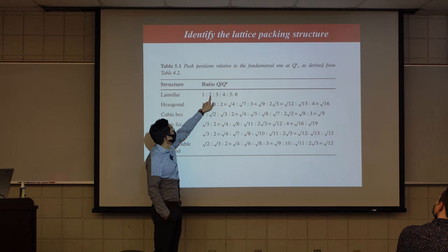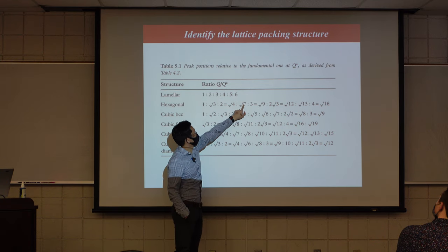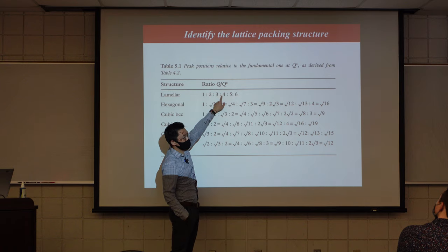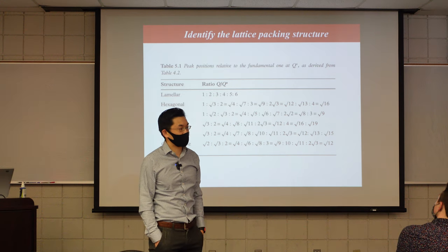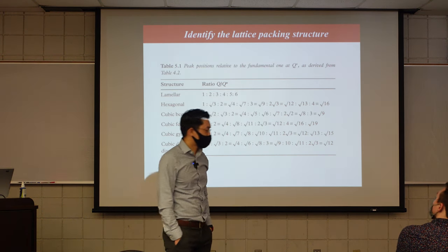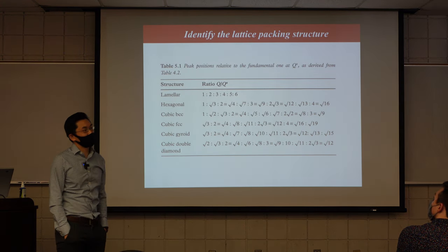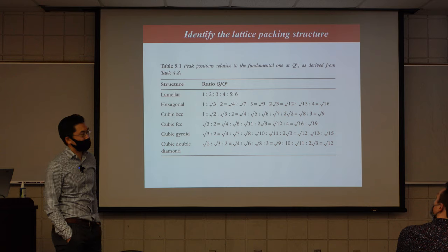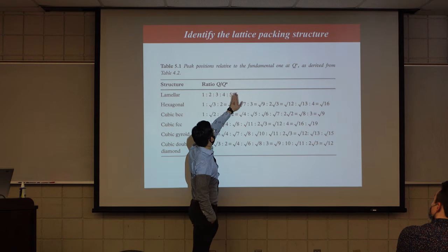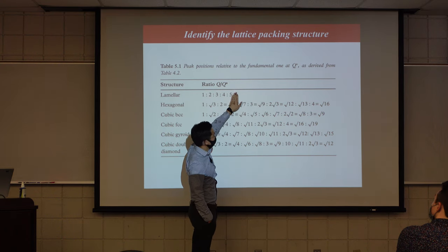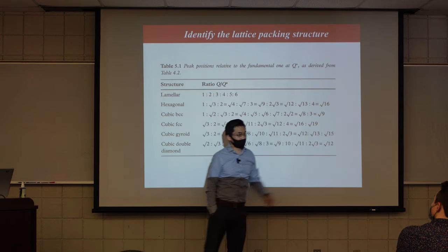And why is it, let's say in this case, you're missing root 3 and missing root 7, right? It's basically canceled out by the symmetry of your packing structure, okay? So that's how you can adopt these cool techniques to identify packing structure. Block polymer sometimes is not strongly scattering, so you typically don't see more than fourth order. 5 and 6 are really weak. But for inorganic crystals, you can easily identify high-order peaks up to 7, 8.